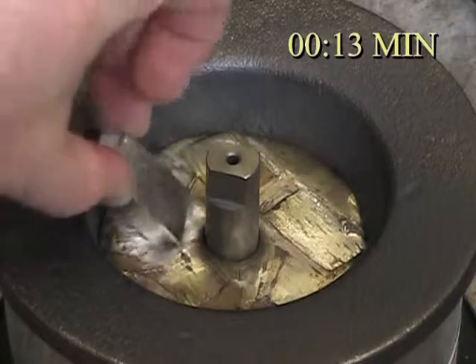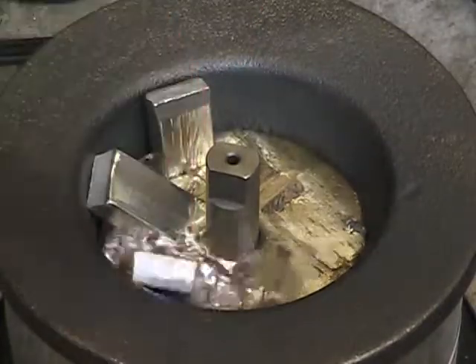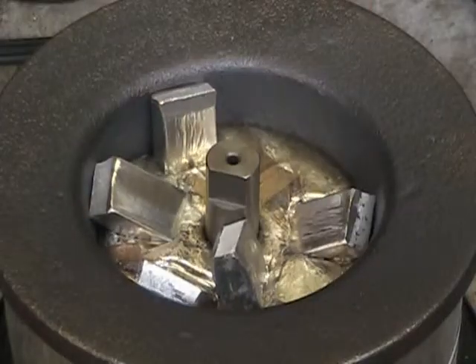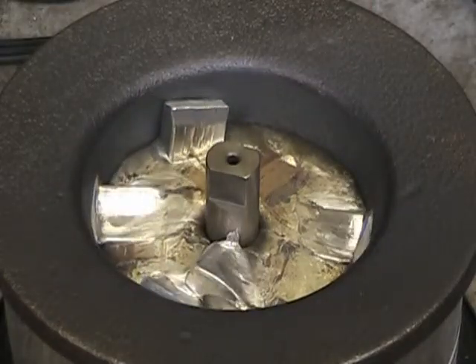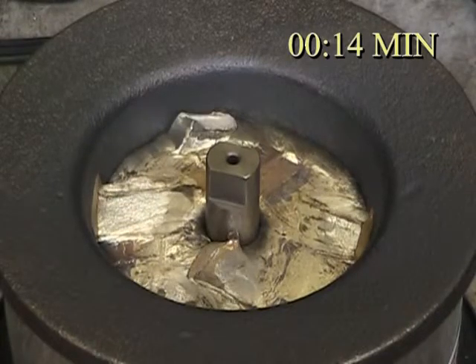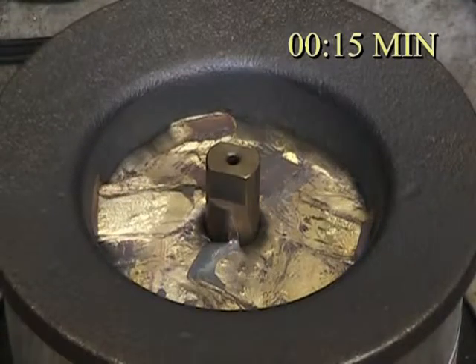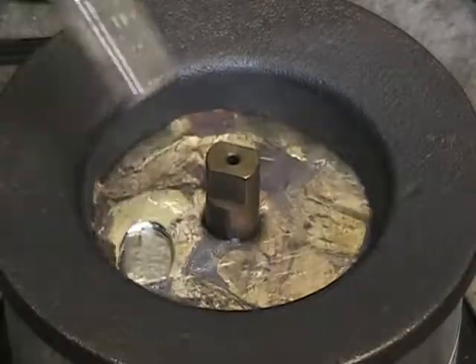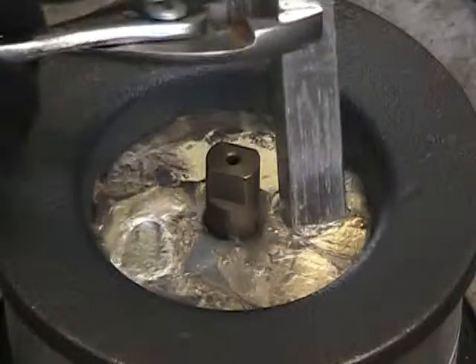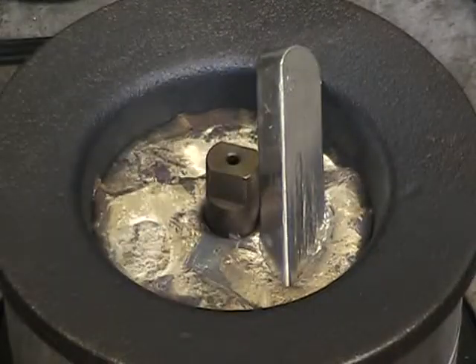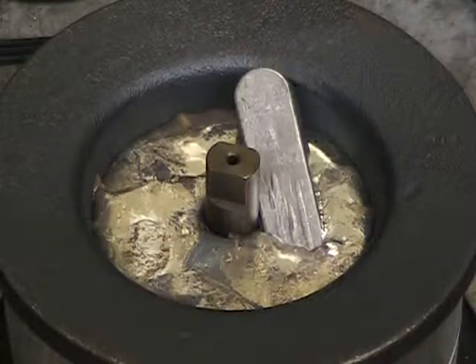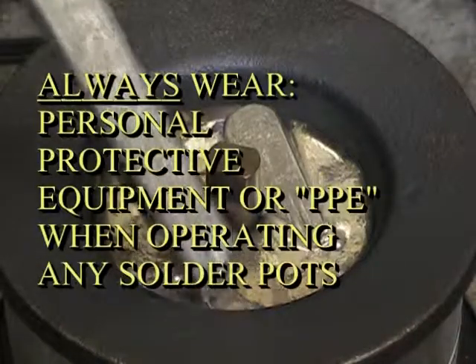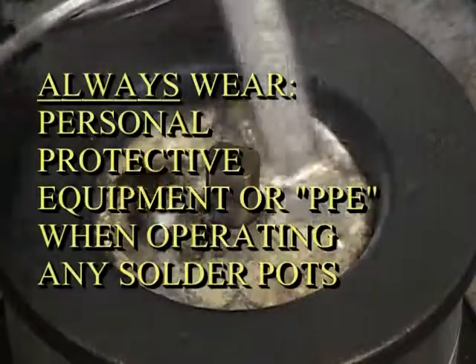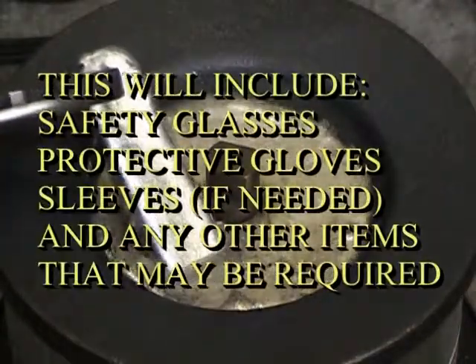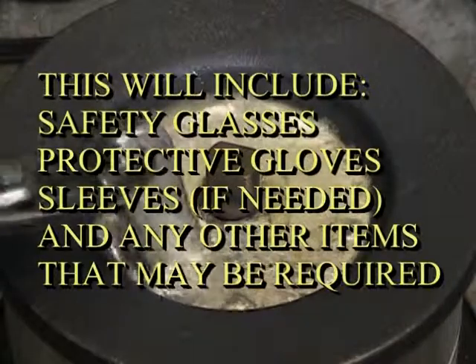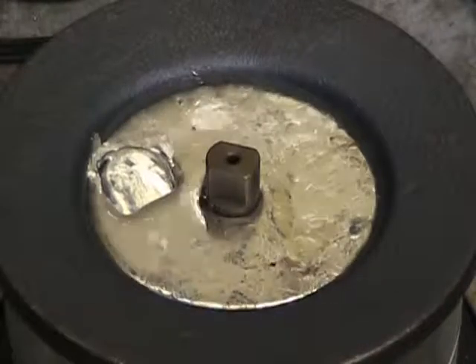As more solder is added to the bath, use care to avoid splashing the already molten solder. The crucibles of the American Beauty solder pots are made of gray cast iron because of its natural resistance to the solubility of tin. This becomes more important now as many lead-free solders are manufactured with a much higher tin content. Larger pieces of solder can be added and will melt more quickly as the molten solder level rises in the pot. When adding larger or full solder bars, you will need pliers as the bars will transfer heat and get hot very quickly. It is always important for the required personal protective equipment to be used when charging, operating, or purging your solder pot. It is also important to understand and operate in complete compliance with all federal, state, and local regulations.